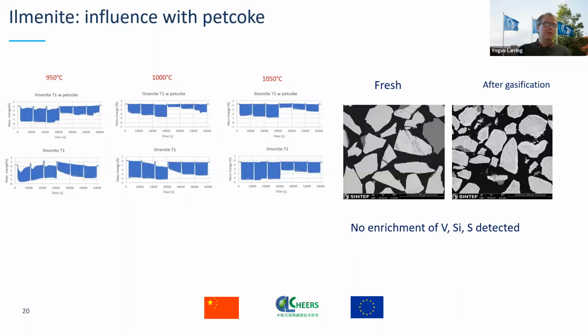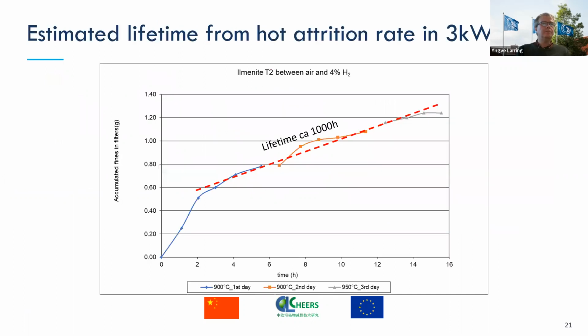But I think for these kinds of cases, you really need something operated for a long time in a reactor. They estimated lifetime from hot attrition rates in a 3 kW rig and got a lifetime of around 1,000 hours, between 4% hydrogen and air. The lifetime will depend very much on the depth of reduction of this material, so it's a little bit hard to get a good number there, but it might vary, of course, plus or minus at least 200-300 hours depending on the operation.